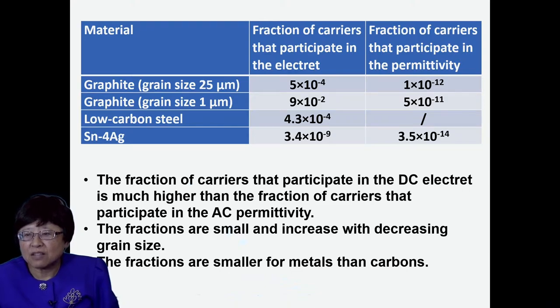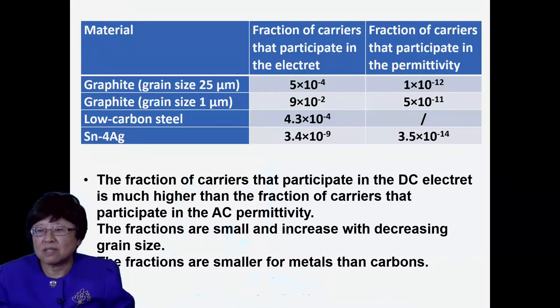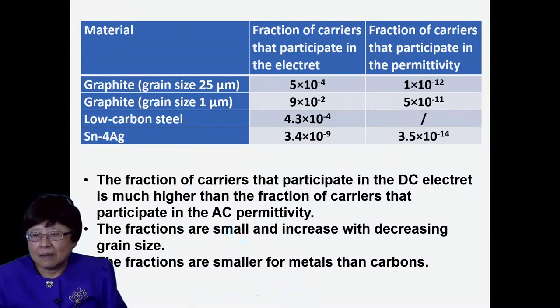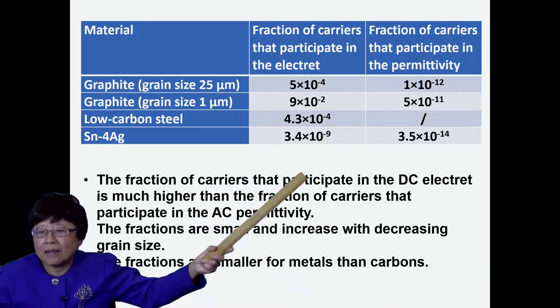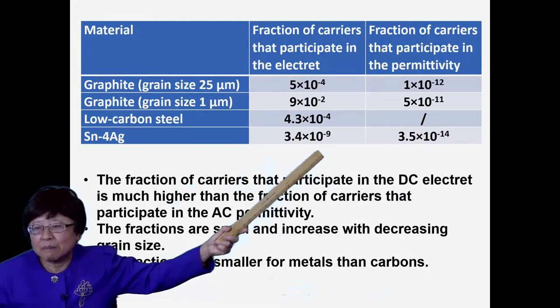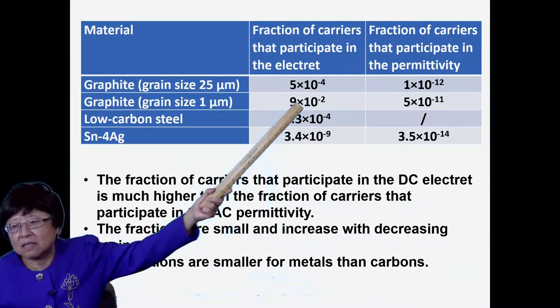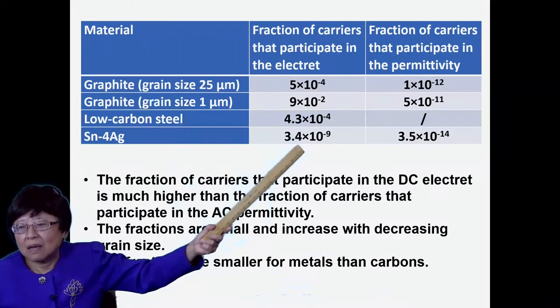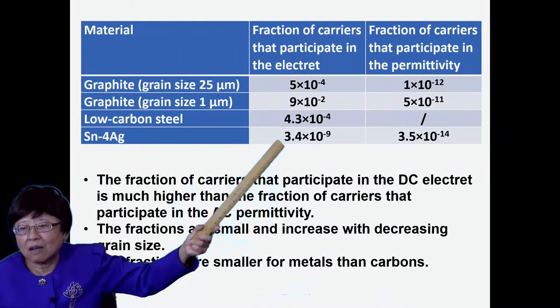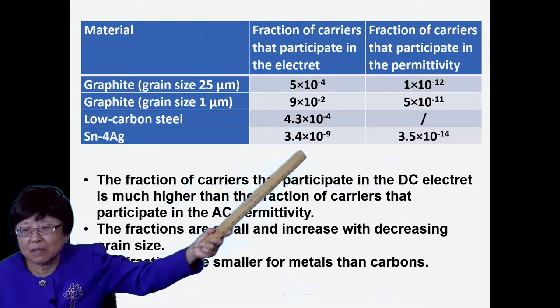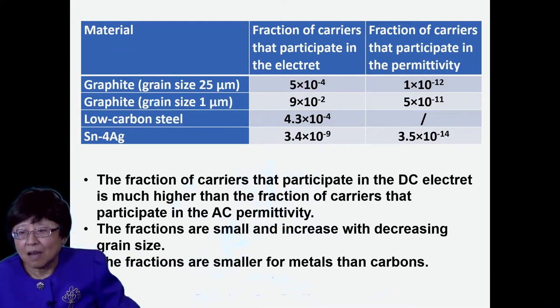Expressed in terms of the fraction of carriers that participate in the electret. That fraction is just the number of carriers that participate in the electret divided by the total number of carriers available. You can see that that number is not large. It's like 10 to the minus 4. Particularly for high conductivity metal, it's even smaller because of the large number of carriers in the denominator.